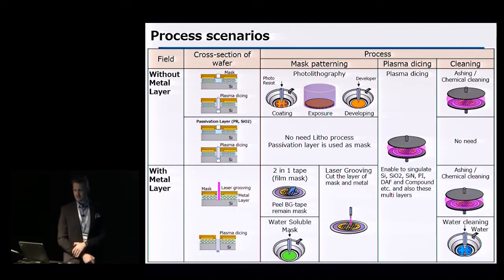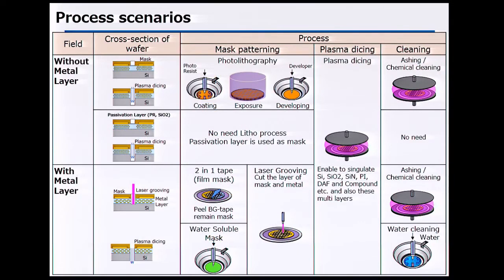So there are two ways that we achieve this plasma dicing process. Either we perform a photolithography masking method, or we can do it with laser patterning. Important to note, the laser is not etching or cutting the wafer, it's merely making a pattern on top of the wafer, on the same principle as photolithography. But laser patterning has the added benefit that if you have a metal layer, you're able to also etch this out. If there's metal in the top layer, the plasma cannot etch that.